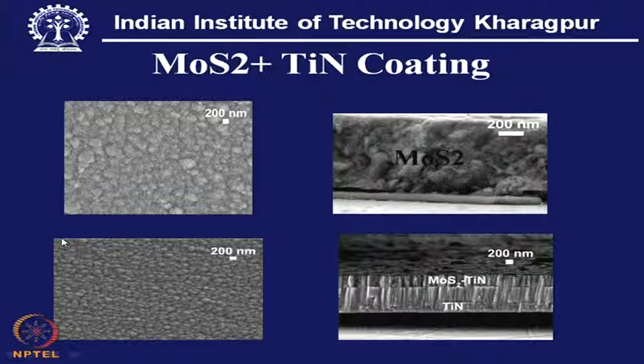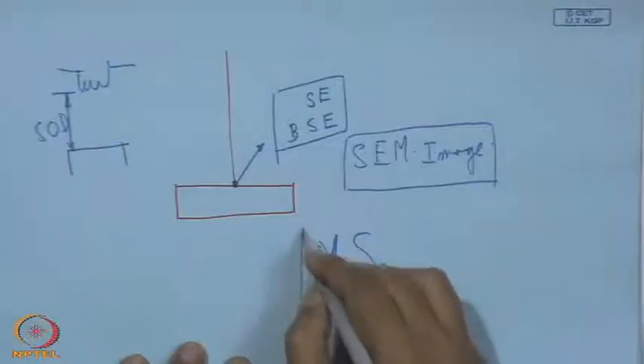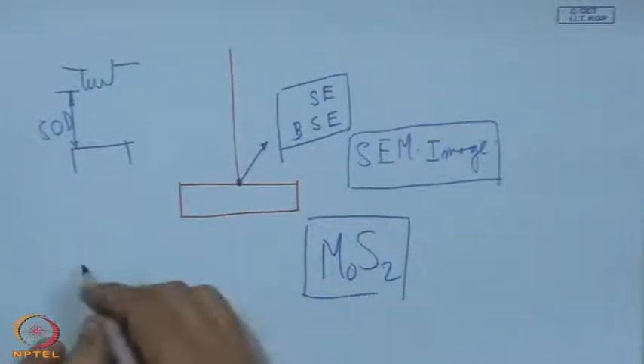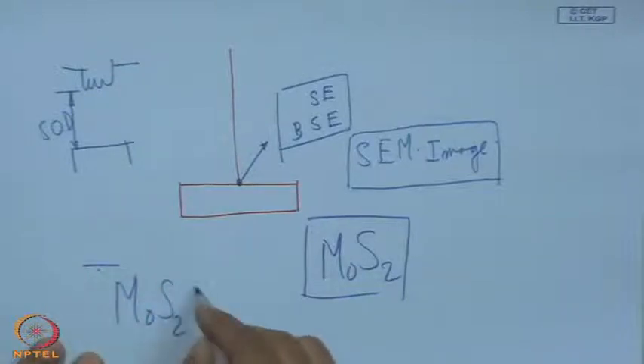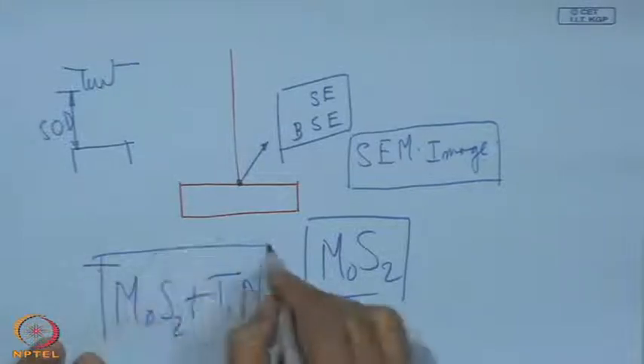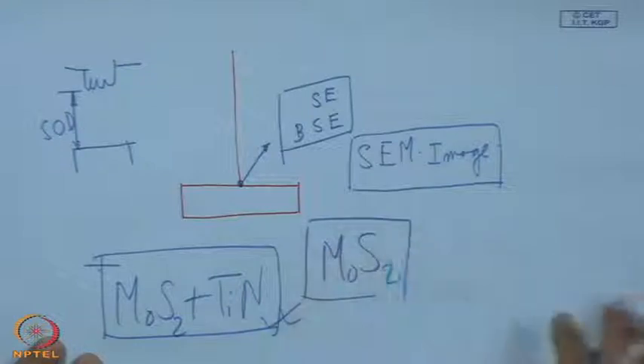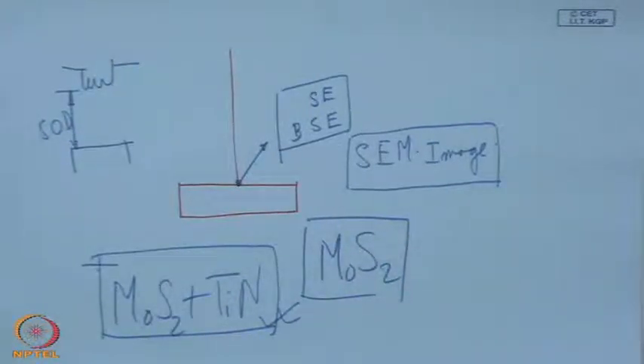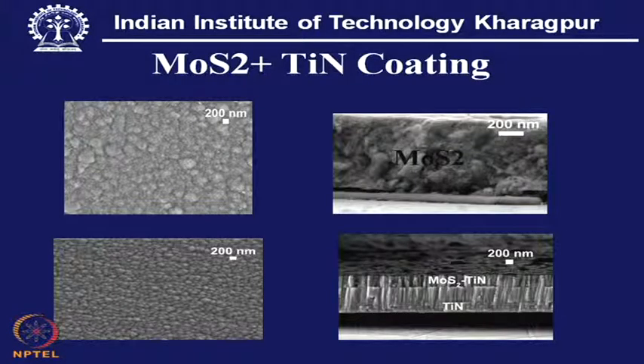Now, here we can find a very interesting picture. This is also a study with SEM, and it helps the coating technologist, or the application engineer, to understand the difference when it is MoS2 alone, or when it is not just MoS2 but MoS2, molybdenum disulfide, plus titanium nitride. Here physical characterization is extremely important, because that is a new development, and we know MoS2 in its individual entity is a lubricious coating, and it has some limited application.